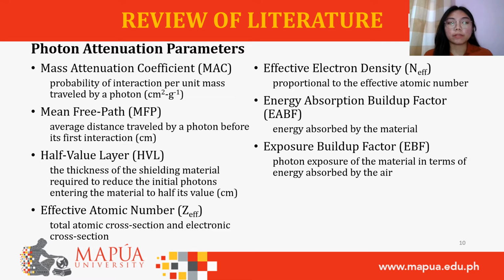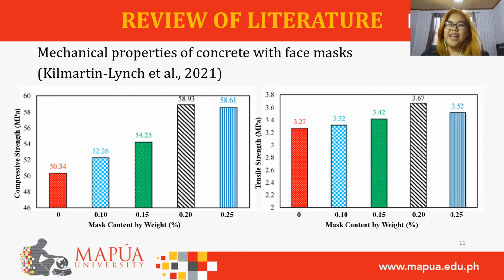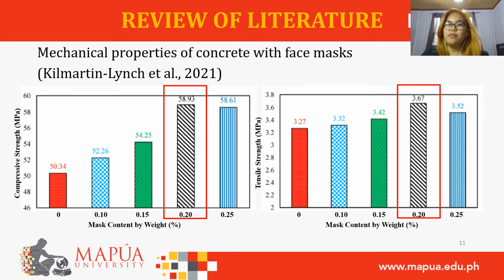and exposure buildup factors. In light of the prevalent use of face masks, Kilmartin-Lynch and others investigated the mechanical properties of concrete with face masks. Results showed that increasing the face mask in the concrete mix will increase the compressive and tensile strength of the concrete. However, this is only advantageous up to 0.2%, as there was an observed decrease in the strength beyond 0.2%